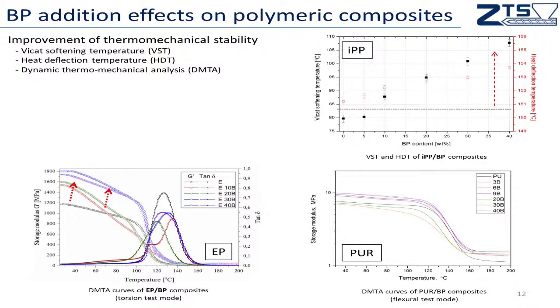We can see that 3 different methods are used here: Vicat softening temperature determination, heat deflection temperature, or dynamic thermomechanical analysis. Here we can see the collectively presented results for 3 different polymers with various techniques. At the top of the slide we can see the variation of the Vicat softening temperature and HDT of the isotactic polypropylene-based materials. And here we can see more than 20 degrees improvement of the Vicat softening temperature, which really improves the usability range of this material.